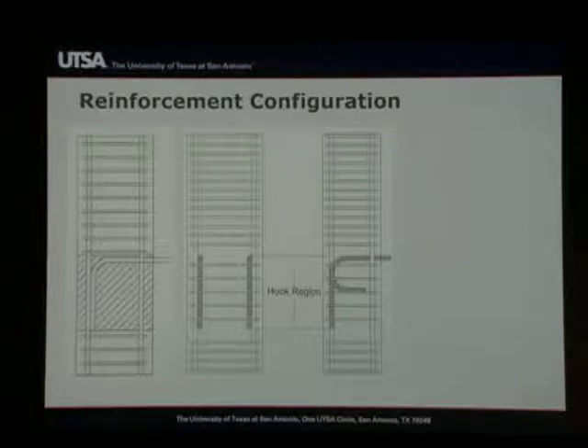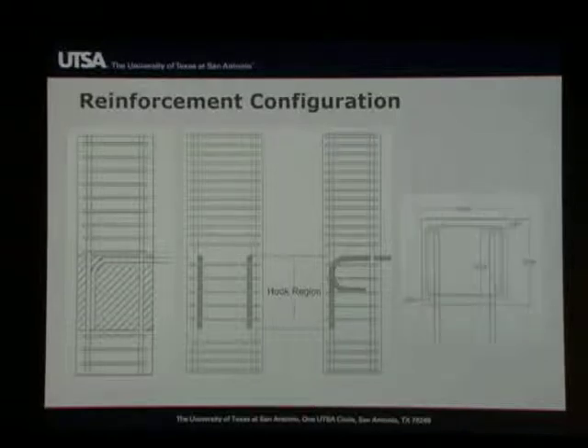In others, we use various amounts of reinforcement within the joint region. We use hooks that had a 90-degree bend, like shown, or a 180-degree bend. And then, of course, one of the aspects that we wanted to study was the effect of the placement of the hook. In a typical joint, construction-wise, folks would place the reinforcement inside of the column reinforcement. It makes more sense from the construction point of view. But there are instances in which we're going to deal with members that are not in joints. And so we also did tests where we took those bars and we placed them outside of the reinforcement, thinking that that column reinforcement and certainly the transverse reinforcement would have some confining effect that would help the strength of the hook. So we wanted to evaluate both the best case scenario and the worst case scenario.